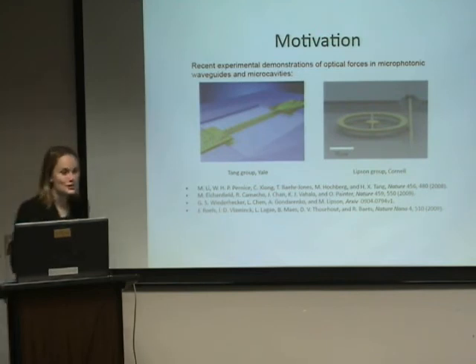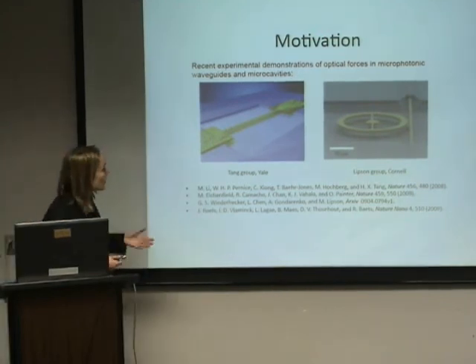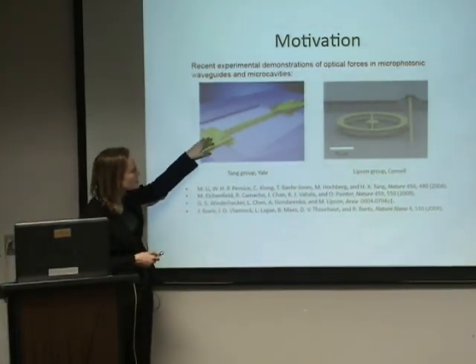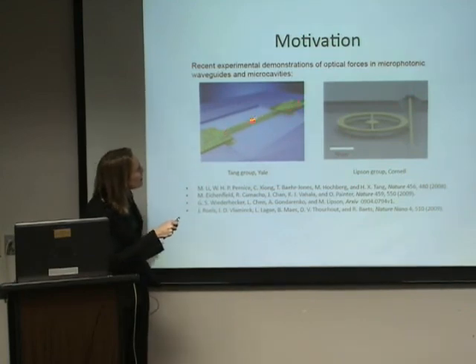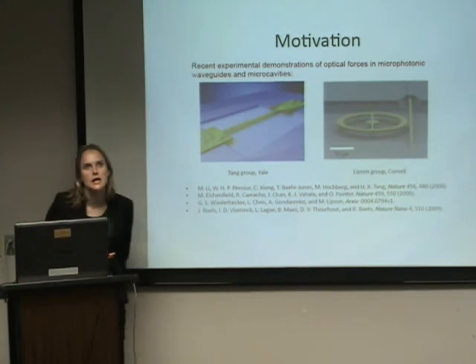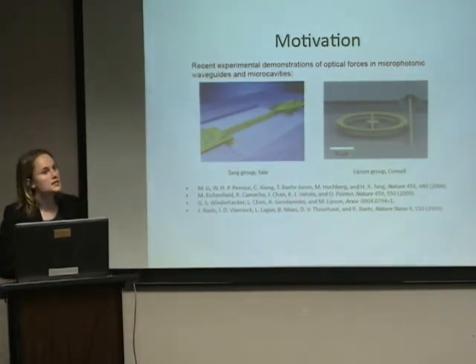With this motivation then, seeing that this actually can work, to give you a sense of the scale, this is about 30 microns. These are a few hundred nanometers by a few hundred nanometers. The optical power is somewhere around 10 milliwatts. And the displacements you see are something in the range of 5 to 10 nanometers.